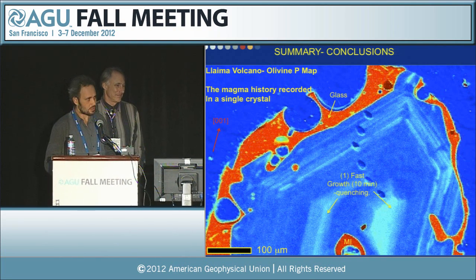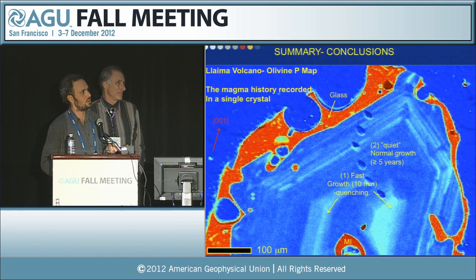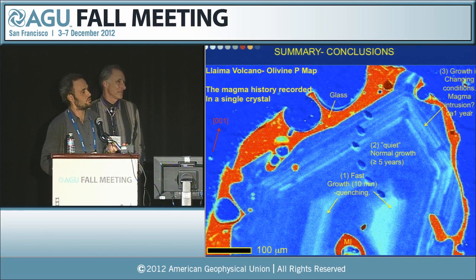And basically, we have 4 steps: fast quenching, about 10 minutes, this at a quiet period, at least 5 years, this zone, which we don't know exactly what to make of. Probably there's 2 intrusions here, less than a year. And finally, this solution. And thank you.